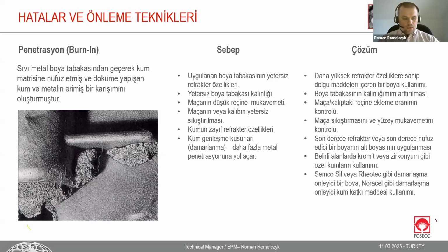So even that kind of points as a quality of the sand, reclaimed sand, binder itself, addition of binder, application of the coating or coating itself, the layer was enough or not, impregnation coating was used or not. So solution in a right side. So what I exactly tell you now, so how to prevent is exactly to do that. We need to use exact and good selected coating. We need to take care about the binder addition, apply pre-coat. Pre-coat, it's this impregnation coating.